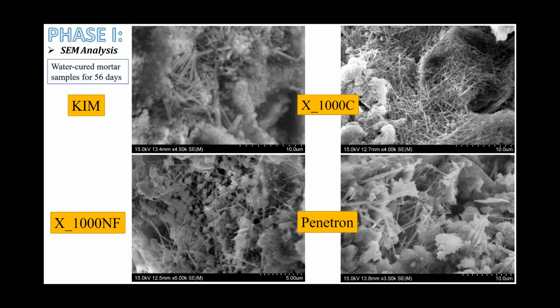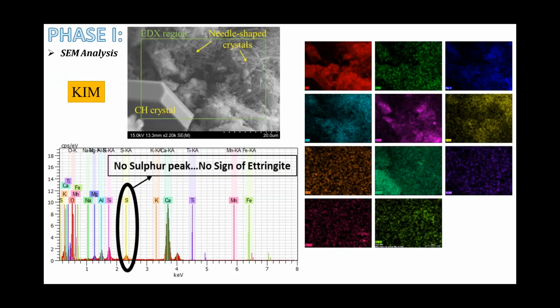In order to identify the difference, I did X-ray analysis on the products produced by Kryton and also the other products. As you can see in the X-ray spectrum, one of the critical components I needed to look into was whether these crystals are ettringite. As I mentioned earlier, ettringite is not a good thing for concrete. It can be indicated by the presence of sulfur, and here you can see there's no sulfur peak, which means there's no sign of ettringite.